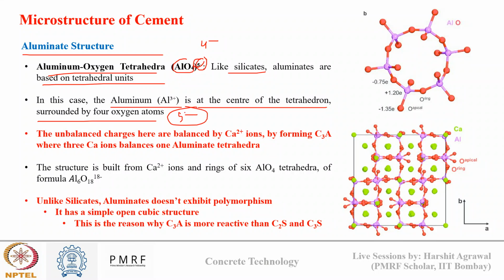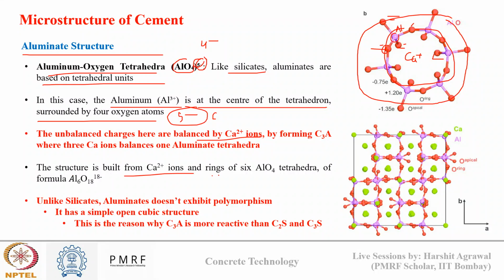To balance these unbalanced charges, we have calcium ions. These calcium ions balance the unbalanced charges in the form of a ring kind of structure. You can see this is aluminium, pink one, and this is oxygen bonded with aluminium, and they form a ring kind of unit, and the unbalanced charges on the oxygen are balanced by the calcium ions. So the structure is built with calcium ions and rings of 6 alumina tetrahedra which form this unit. However, unlike silicate, aluminates don't exhibit any polymorphism, so it is not oriented towards a longer time.